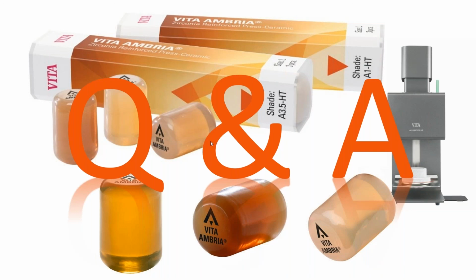Now you can use a disc to contour the embrasures, but then I would use a small diamond burr that's round and grind out your interproximals a little bit deeper, but you're keeping it more bowl-shaped than a V shape, wedge shape. So make sure that you use the proper instrumentation, and I would also use caution. Make sure you use some water.